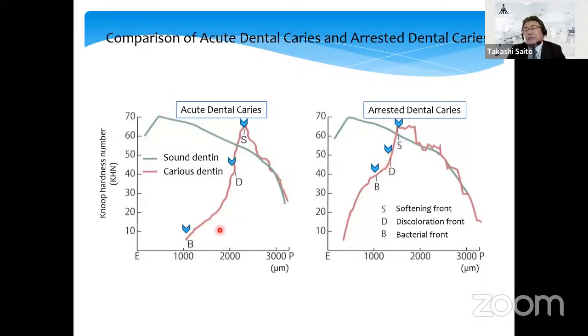Moreover, in case of acute dentin caries, the bacterial front here is far from the discoloration front and softening front, around maybe 1.5 millimeters. On the other hand, in arrested dentin caries, they are very close, around 0.5 millimeter. So we can say, in case of arrested dentin caries, the hardness and discoloration can be an indicator for cutting, removing the infected dentin, actually an indicator of the bacterial front. But in case of acute dentin caries, they cannot be indicators.